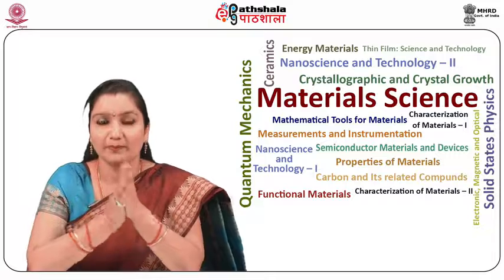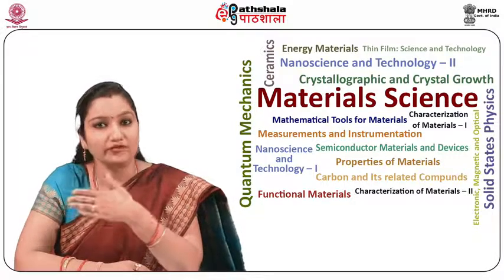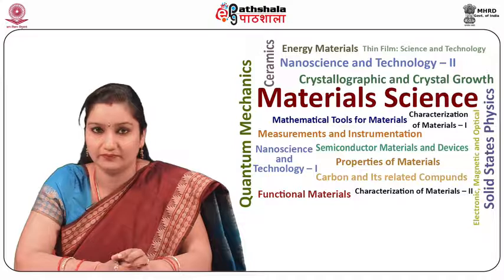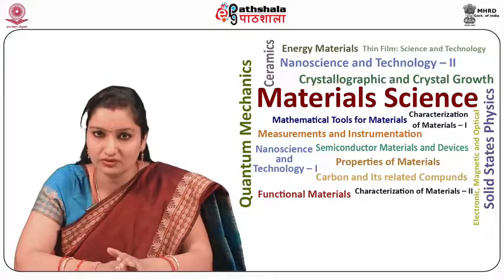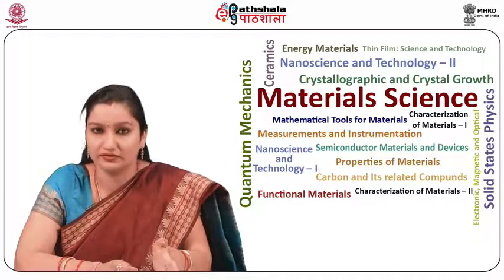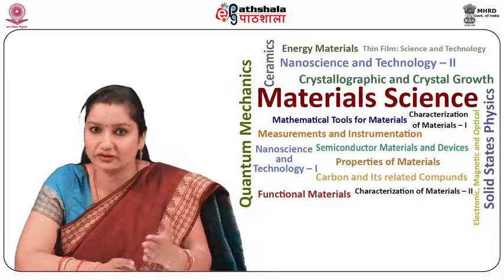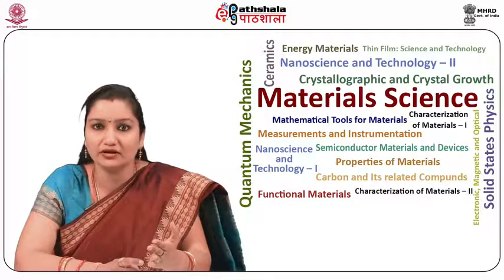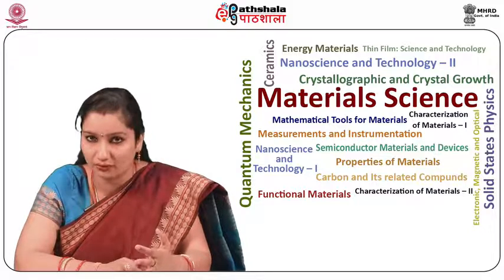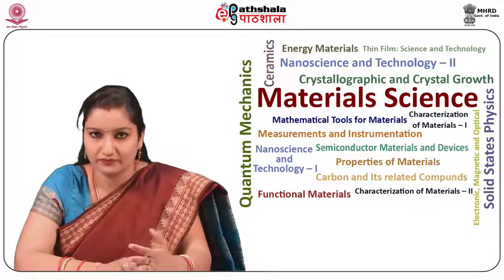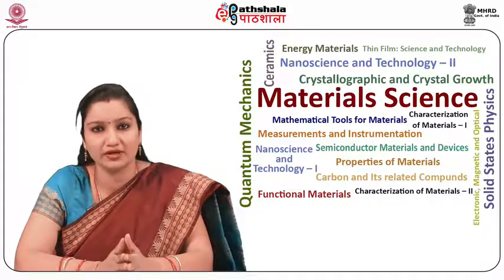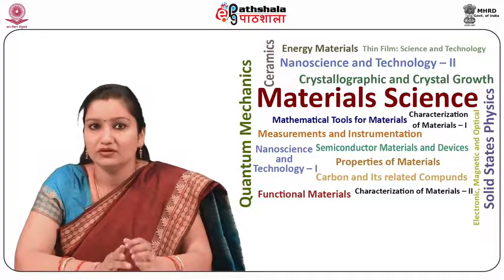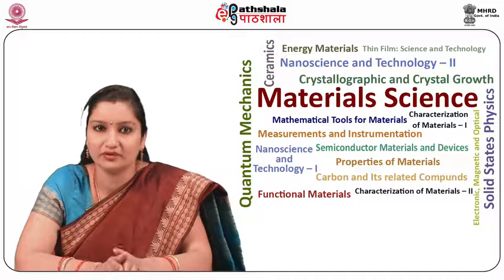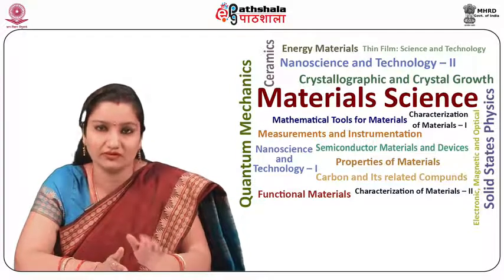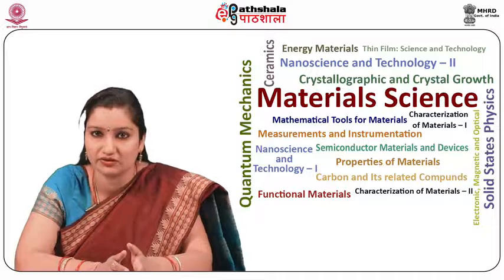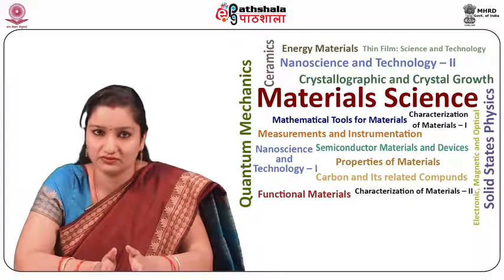The first one is that creep is much more affected by the grain size, that is the microstructure, and the previous strain history. So the three factors are the grain size, microstructure, and the previous strain history, for example, cold work. Creep is also extremely structure sensitive. That is, the major factor which will affect any creep will be its structure, and the structure obviously includes the grain size, its microstructure, and the previous strain status.